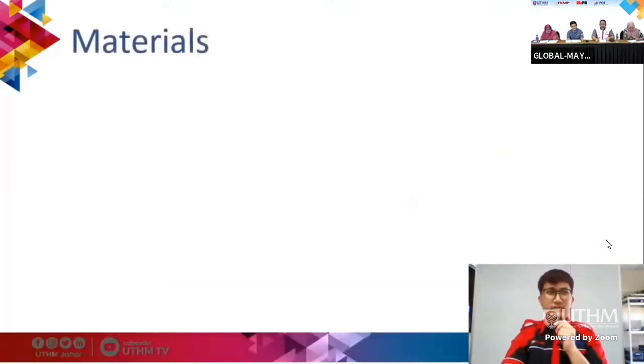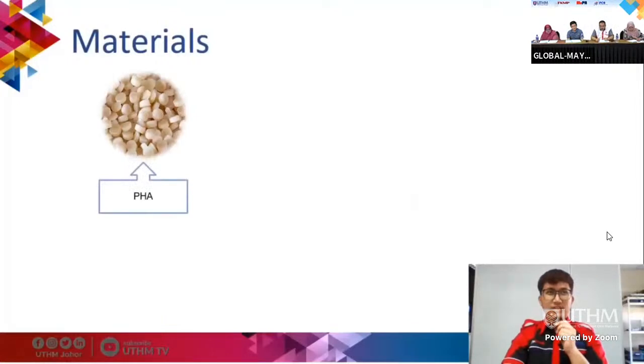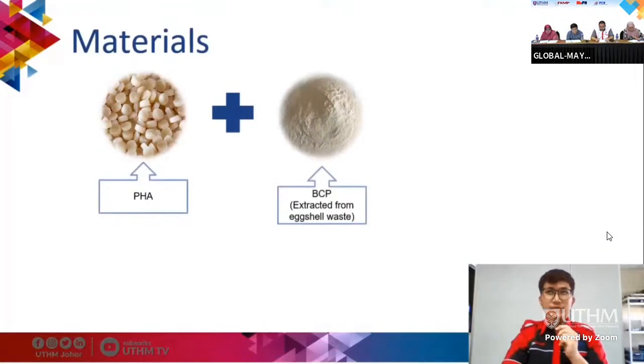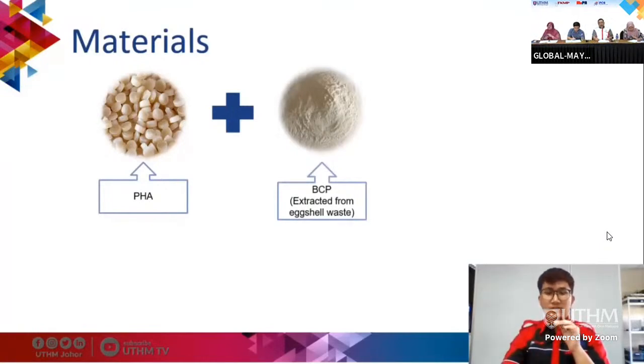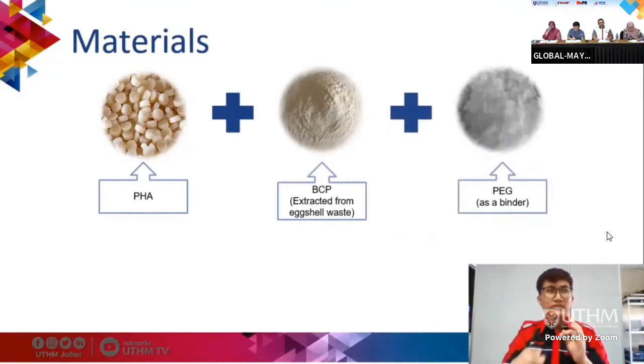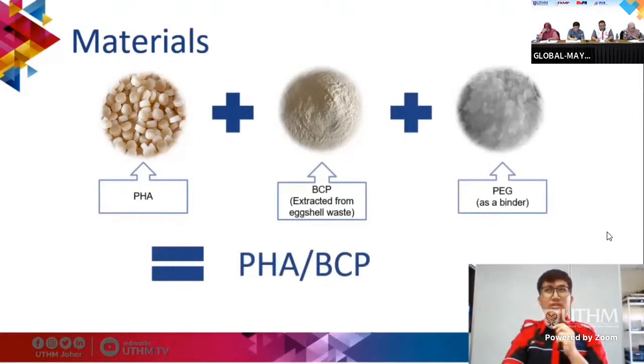For our material, we use PHA as a matrix and biphasic calcium phosphate as a filler, which we extract from eggshell waste powder. We synthesize it to make a powder, and then we combine it with polyethylene glycol as a binder to combine the PHA and BCP, and we produce PHA BCP. We mix using a Brabender machine.